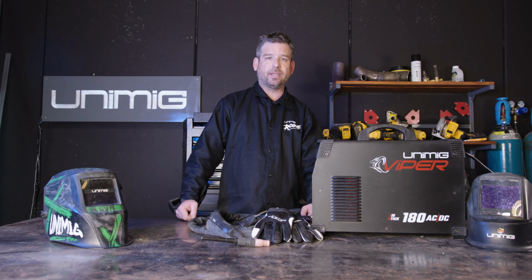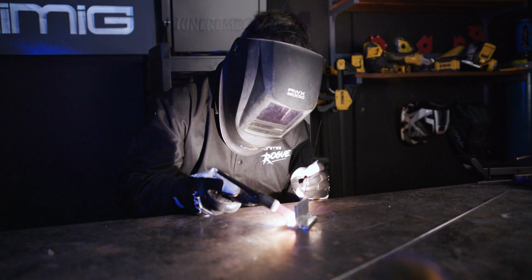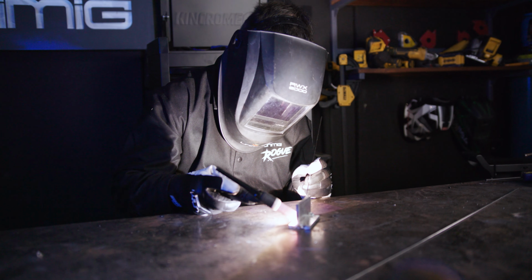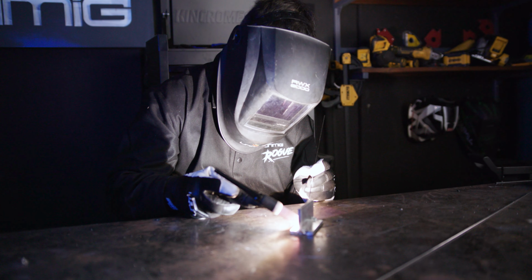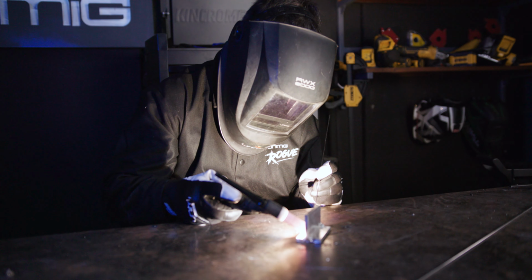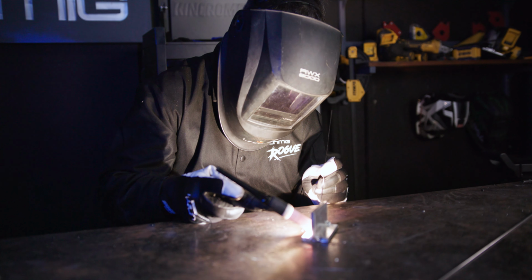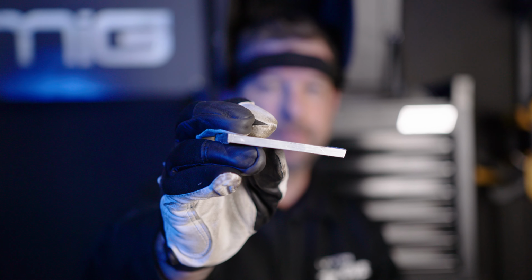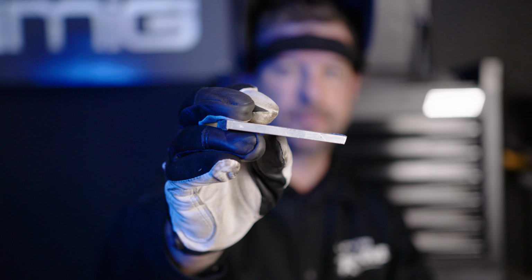Starting with mixed arc AC/DC welding, this is a combination of TIG AC and TIG DC negative in one weld. There are quite a few benefits from this type of weld, including high welding speeds and penetration and a faster weld puddle on cold workpieces. Mixed AC/DC also means that you can weld on thicker materials.